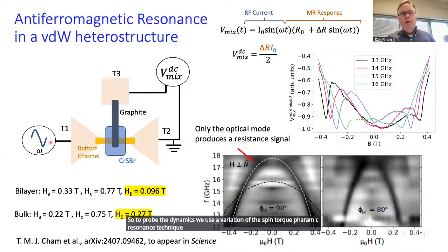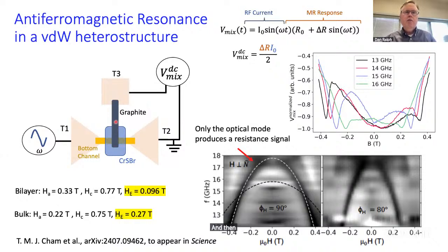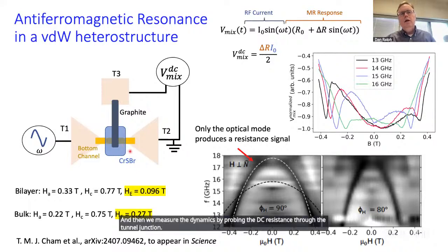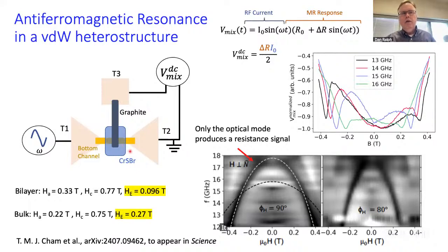We apply an RF current through the bottom channel that can excite magnetic dynamics in the antiferromagnet via both an Ørsted field and possibly from spin orbit torque. And then we measure the dynamics by probing the DC resistance through the tunnel junction. It happens there's some leakage of the RF current through the tunnel junction.